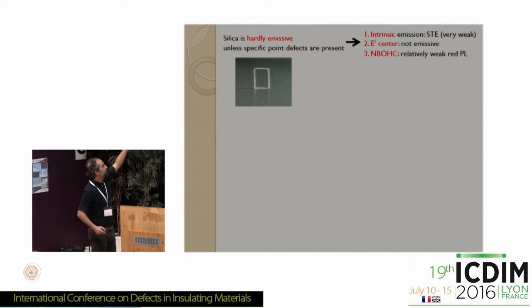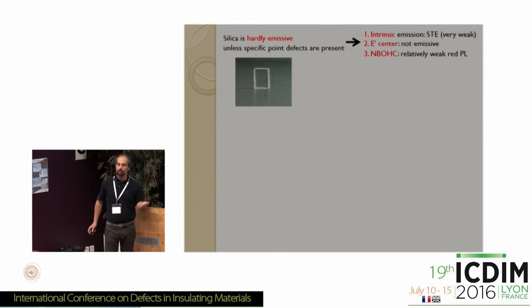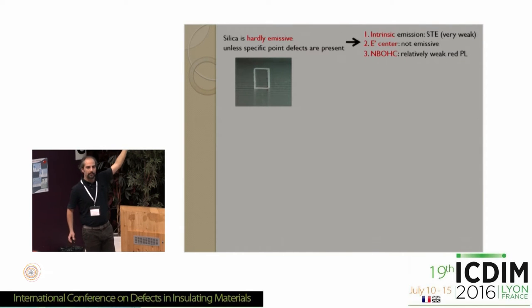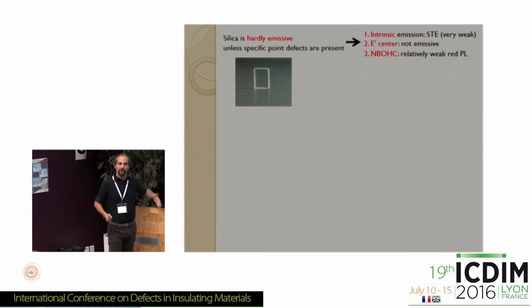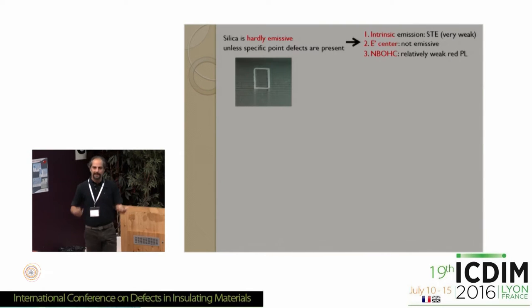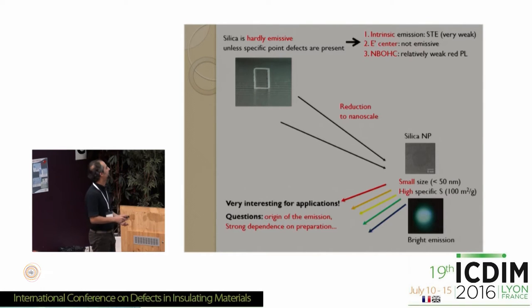If you want to use point defects to get emission, well, the silicon dangling bond does not give you any luminescence, and the other common defect, the oxygen dangling bond, gives a red emission, 1.9 eV, which is relatively weak. So the most common defects, as well as the inherent properties of the system, do not make silica a good emitter. Of course, this can be solved by doping. You can introduce everything that emits in your material. But another way to overcome this problem is to go to the nanometric scale.